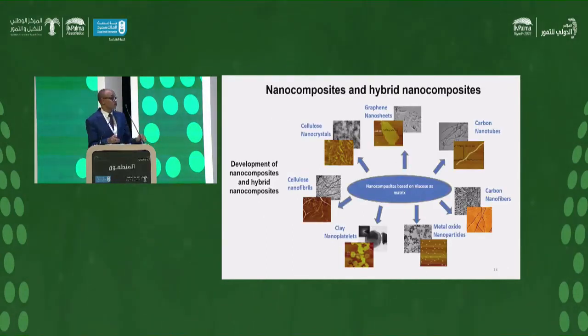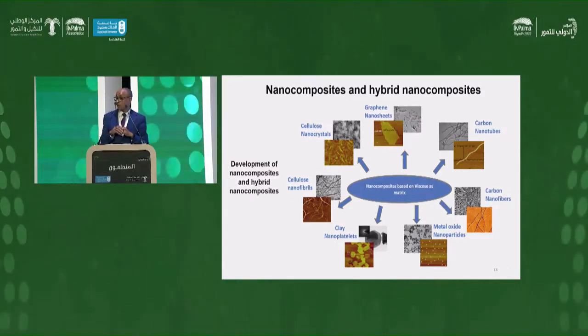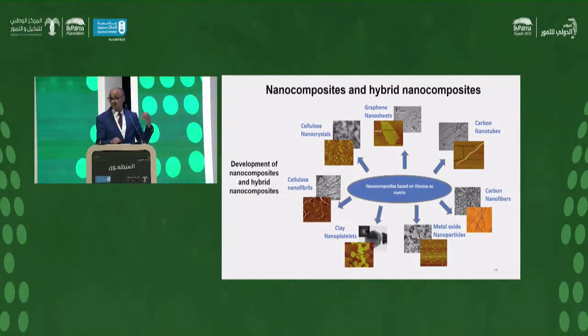And for this, in our laboratory, we work on the synthesis of different nanoparticles: cellulose nanocrystals, graphene nanosheets, different routes to obtain graphene and its derivatives, carbon nanotubes, carbon nanofibers, metal oxides. We need these for specific applications. For example, when we want electrical conductivity of the film, we need to introduce some specific particles like metal oxide nanoparticles, which can be used in small quantity, and we can respond to the specific application. Also, the use of clay nanoparticles, and Morocco is rich in bentonite in the north of Morocco.